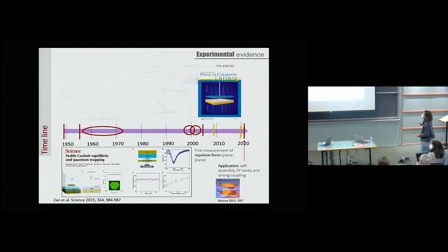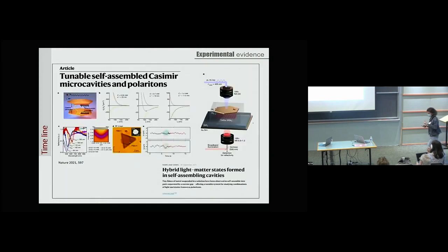We just proposed our theoretical designs, and then very recently the group of Timur Shegai also demonstrated in a similar way, also with gold flakes, the possibility of creating a Fabry-Perot cavity based on this idea of Casimir forces, but in this case the balance is between a repulsive Casimir force and an attractive electrostatic force. And they can go into the strong coupling regime when they include an excitonic material, basically.